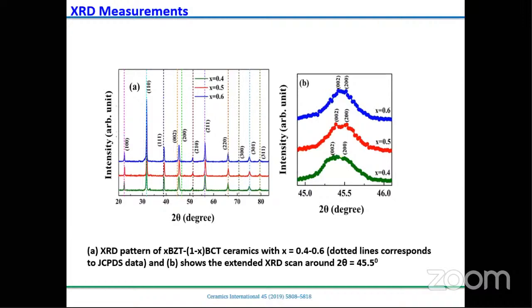Whatever XRD peaks or reflections we observed in this material, those reflections exactly coincide with the JCPDS data, and we observed no extra peak. That means we can say that our material is pure phase. Whatever materials we doped, like calcium and zirconium, we can say that barium is replaced with calcium. Barium has gone, calcium entered.